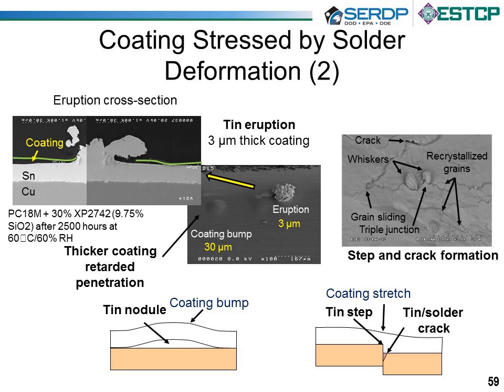So what else did we see? How else does the coating get stressed by the solder or the coating? We have seen lots of pictures of whiskers, but we also saw odd-shaped eruptions, these large structures. We saw them in a couple of places, large structures that form, they're called nodules or odd eruptions in the literature, and we saw some of that as well. So one of the things that coating needs to survive is tin nodule growth under there. We also saw some tin steps formed during thermal cycles and some cracks, and so the coating needs to stretch around those features as they form on an assembly.